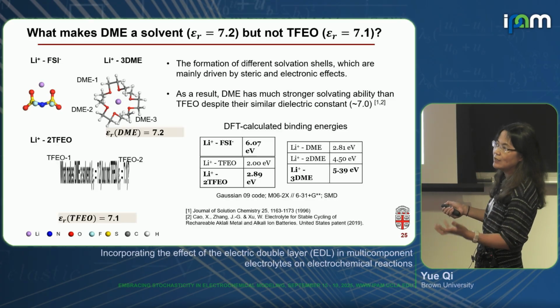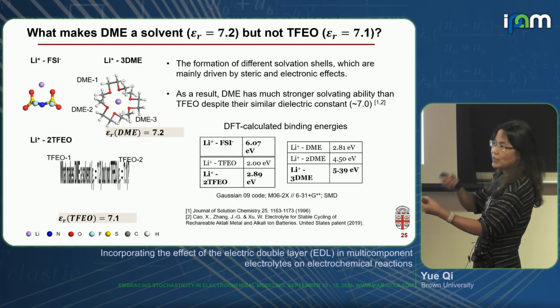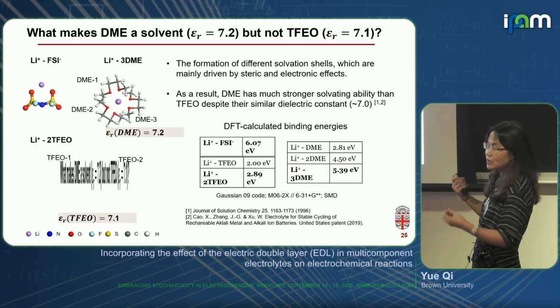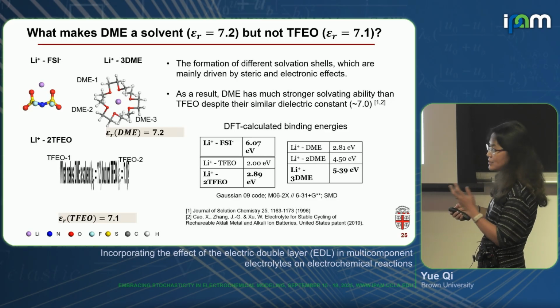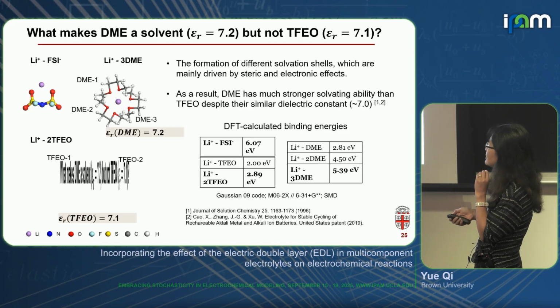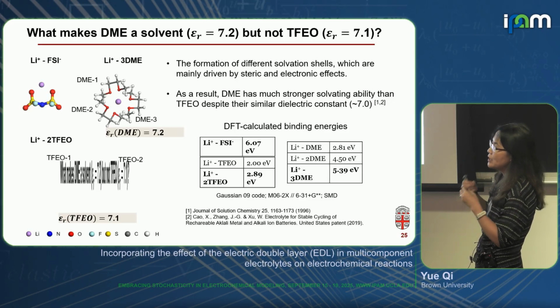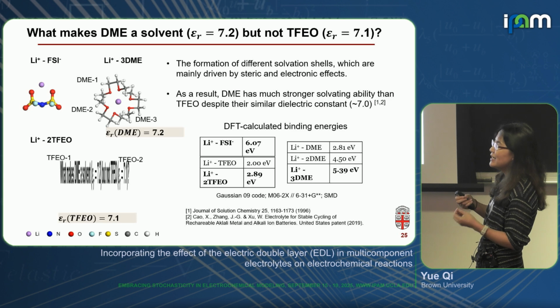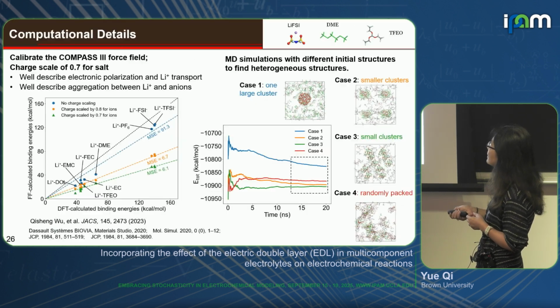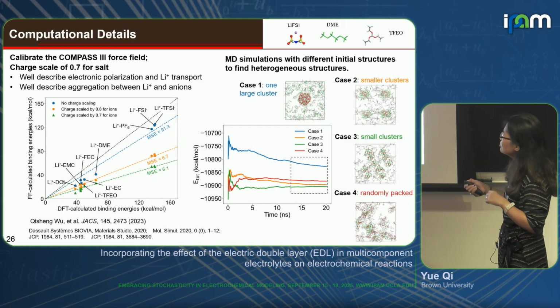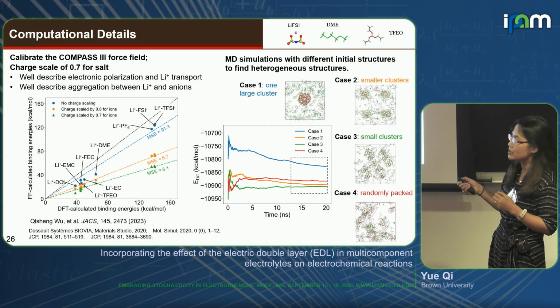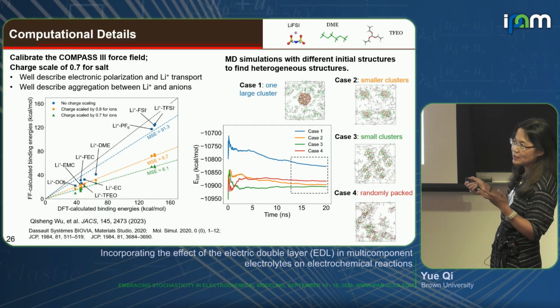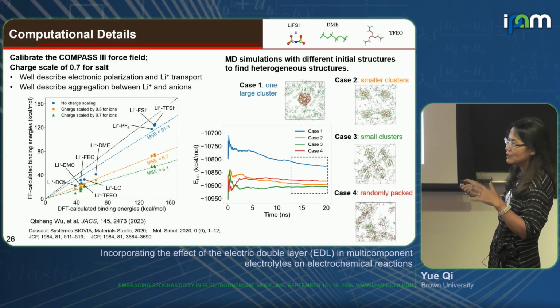So this is their interaction. It's not sufficient to break the lithium out from the salt cluster, right? So this counters some of the argument that the binding energy correlates with solubility. Yes, but not exactly, right? So steric effect is also important. One challenge to get these heterogeneous structures is that MD is never good for finding the equilibrium.